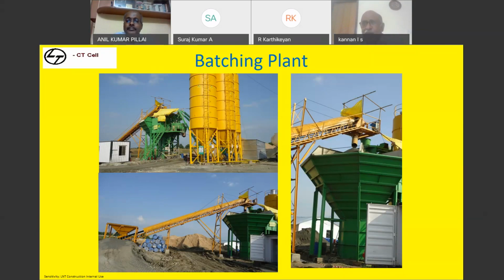Two batching plants went under operation. One batching plant was producing beautiful concrete of 150 mm slump. In the other batching plant, we got only 30 to 40 mm slump. We started the concrete and went to site, and we were asking why it had not come. They said, sir, I'm not getting slump. When I went up, what had happened is sand had got mixed with 10 mm.